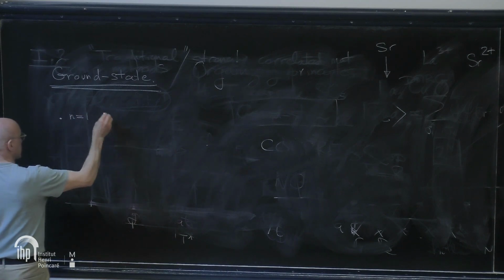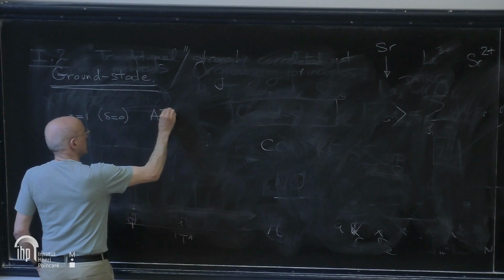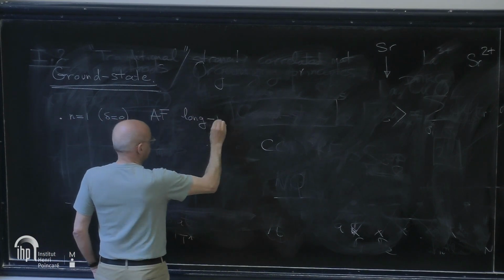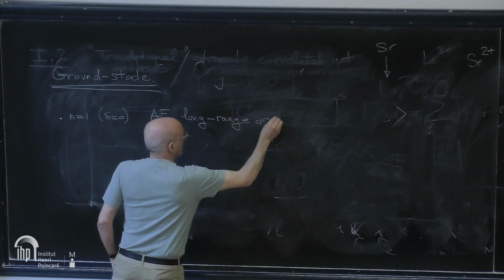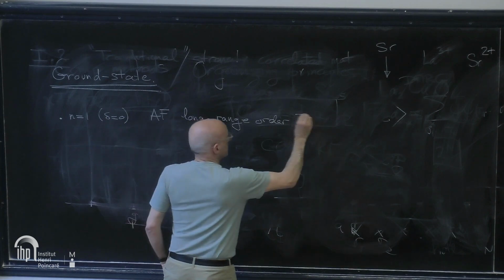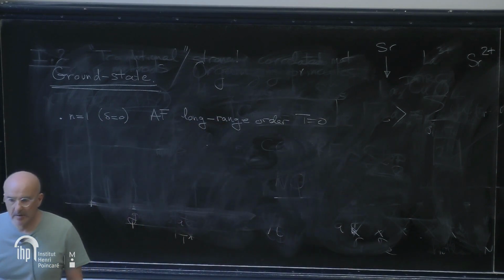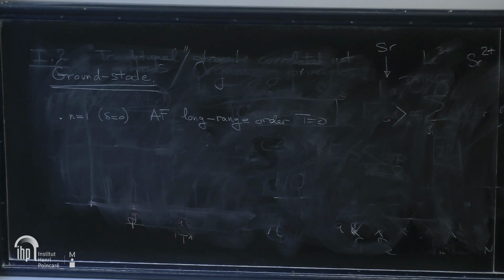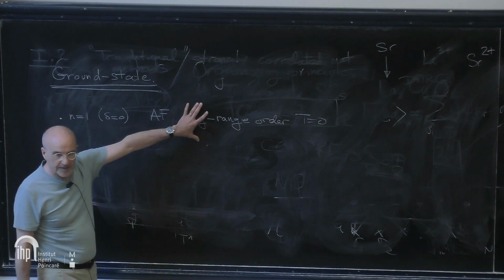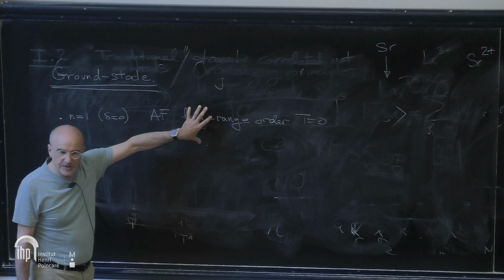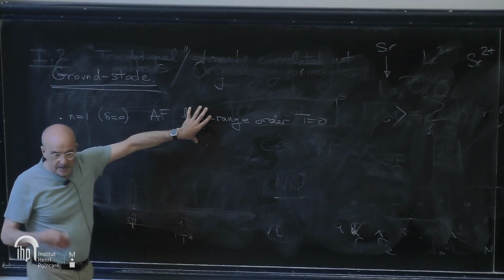Ground state. So what we know for the ground state, of course, at half filling, when the density is 1 per site, or doping delta is 0, the ground state has antiferromagnetic long-range order at T equals 0. Of course, at finite temperature, this spin long-range order is killed by the Mermin-Wagner theorem and fluctuations. And this is why, by the way, it's also very important to understand crossovers, because in 2 dimensions, ordered states resulting from the breaking of continuous symmetry cannot resist finite temperature, and everything becomes crossovers.